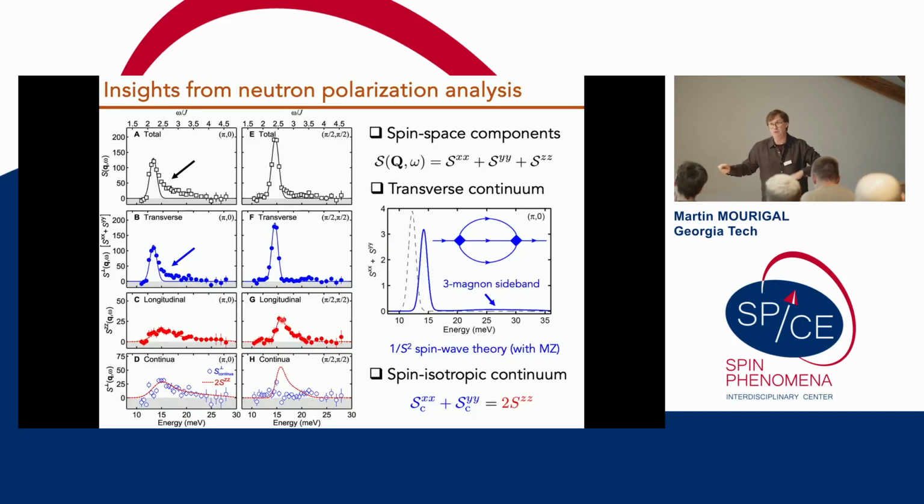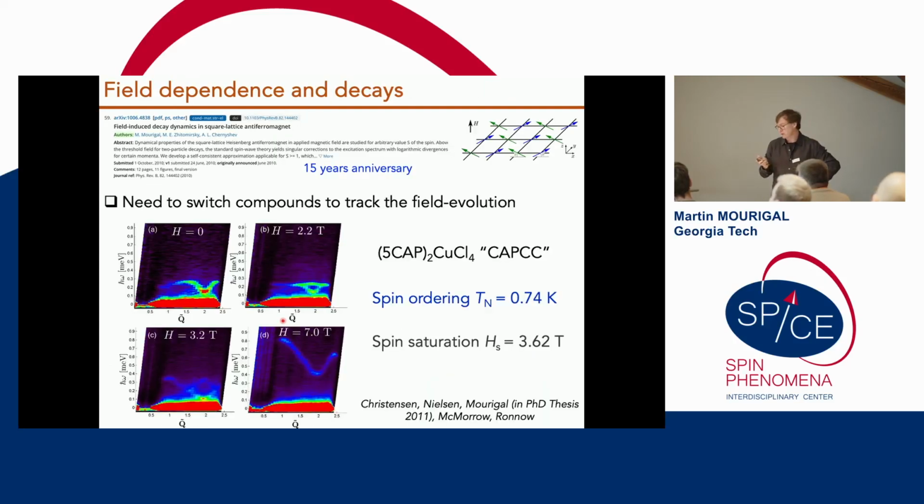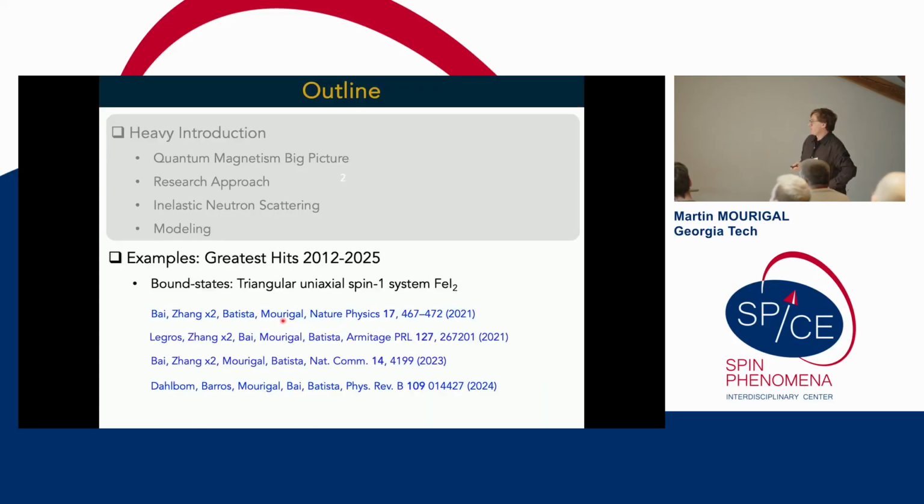The two-magnon continuum lives from the one-magnon energy to the two-magnon energy, but at the bottom of that continuum lives this resonance. So it's not a bound state, it's not living on its own, but it's an enhanced density of spectral weight. Good. Okay, let's continue if you don't mind.